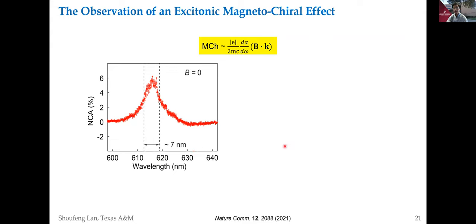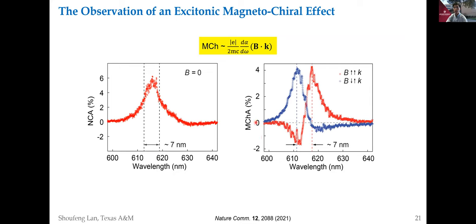And we know that the derivative of a single peak spectrum will be a peak and a dip. Indeed, in the magneto-chiral spectrum, we observe the peak and the dip. And the distance between the peak and the dip is 7 nanometers, precisely the spectrum width of the chirality. This verifies that this magneto-chiral effect is proportional to the derivative of the chirality.